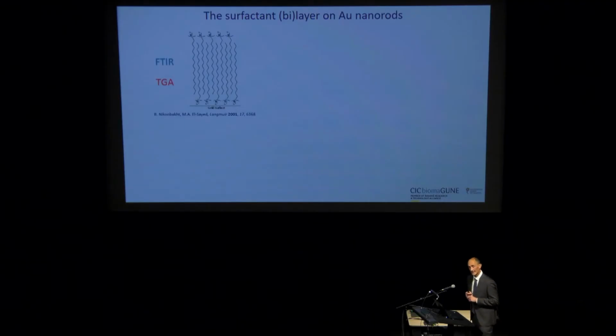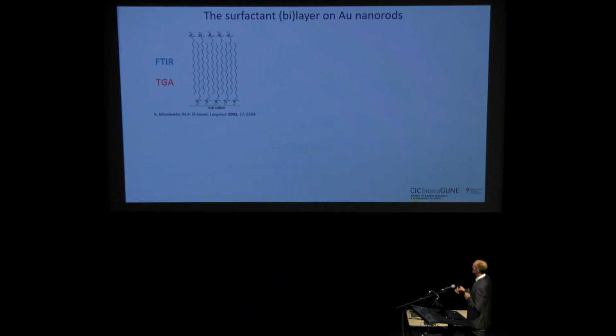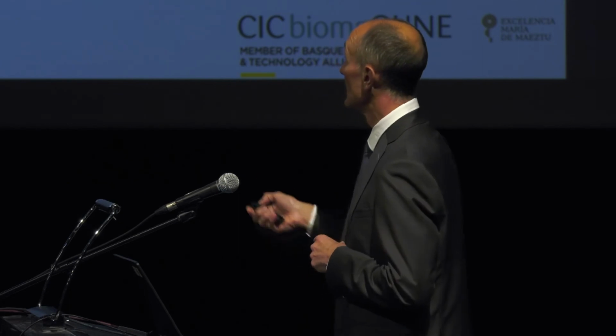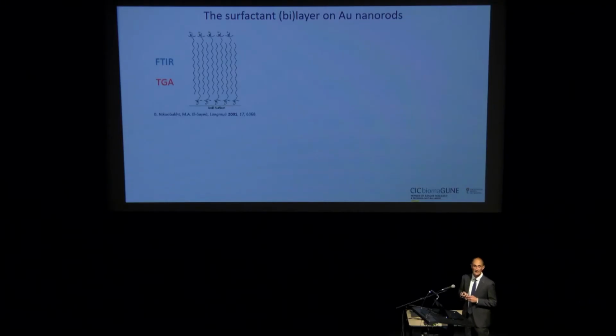Now, again, what about the surfactant bilayer? And so please stop me if I'm speaking too long. I probably become too excited about this. So the bilayer, as I said in the beginning, was explained as basically one of the only possibilities to stabilize these particles in water. And actually El Sayed, who was also one of the pioneers of these systems, applied FTIR and TGA to analyze the surfactant layer on the nanorods. And this was in agreement with the presence of a bilayer, but of course these are bulk measurements.